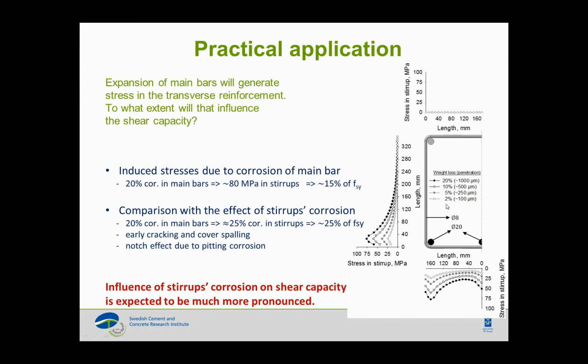So in this case, we are looking at different levels of corrosion for the main reinforcement, from 2% to about 20%. What we see is that for about 20% of corrosion on the main bar, we have about 80 megapascal of stresses in the stirrups, and that means that you have less available stress to be taken due to shear, right? But we also try to understand: is this so important? This 80 MPa of induced stresses in the stirrups, what does that mean?